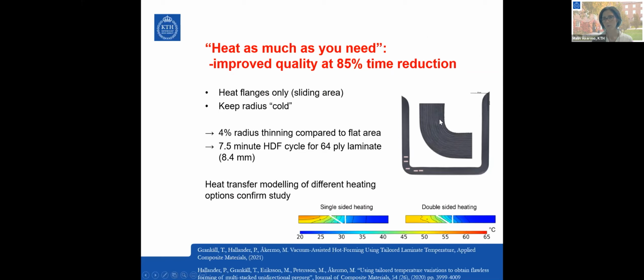And since we only heat a very small fraction of the component, we can make the heating process much more effective. So heating simply the flanges in different ways, single-sided heated or double-sided heated, we have done heat transfer modeling to verify this, and the studies we've done show that we get a much smaller radius thinning than we used to have, 4%, and we have reduced our heating time by up to 85% and still have a robust production.